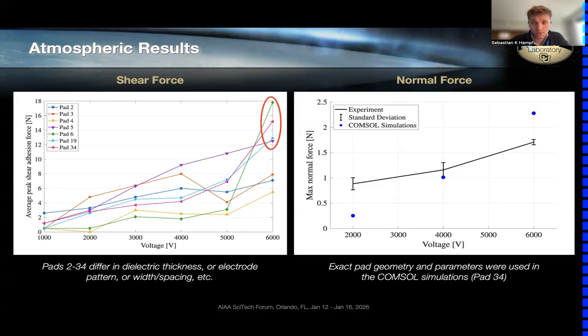Then we also looked at the normal forces that are much smaller and compared them to our COMSOL simulation, because COMSOL can only simulate normal forces. We can see that there is good agreement within an order of magnitude. However, the exact trend differs, and it can be expected from what we're seeing here that we will not see as much of an increase in normal force at higher voltages as COMSOL predicts, because the trend that COMSOL predicts here over this range is much steeper.